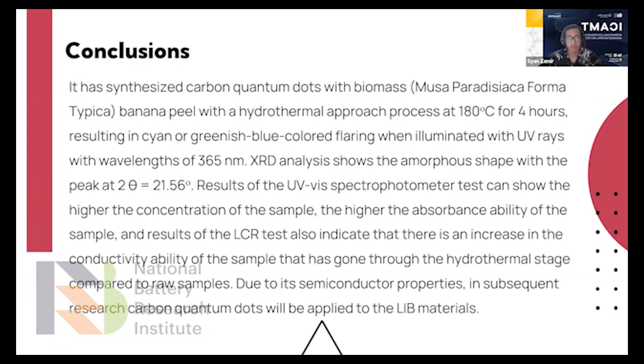We have synthesized carbon quantum dots from the biomass Musa paradisiaca forma typica, banana peel, with a hydrothermal process approach at 180 degrees Celsius for 4 hours, resulting in cyan or greenish blue colored fluorescence when illuminated with UV rays with a wavelength of 365 nanometers. XRD analysis shows an amorphous shape with a peak at 2 theta equal to 21.56 degrees. The result of the UV spectrophotometer test shows that the higher the concentration of the samples, the higher the absorbance ability of the samples.